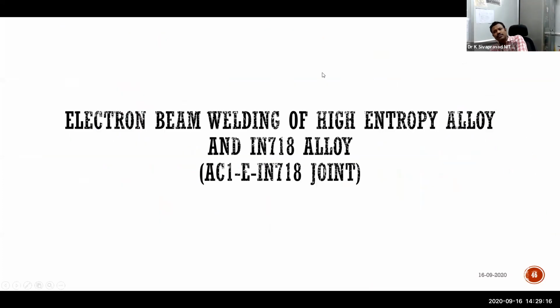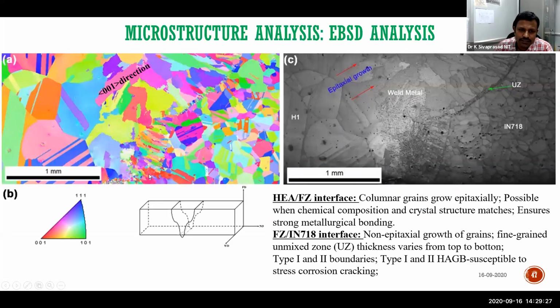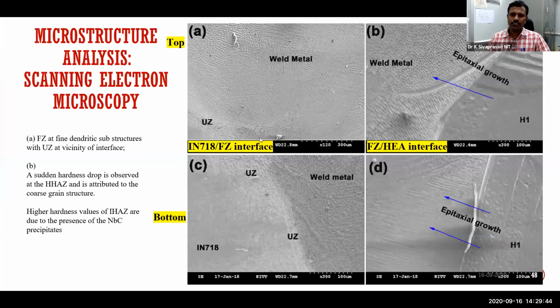Then electron beam welding of high entropy alloy with Inconel 718. The earlier combination was also high entropy alloy with Inconel 718, but that was GTA welding, and this is electron beam welding. And with orientation imaging microscopy, here also on the HEA side it is showing 001 planar direction columnar growth, that is epitaxial growth. Very clearly it is observed and demonstrated. But the fusion zone was very fine compared to GTA welding. See, the cellular structure size used to be very fine. And finer structures, we know, are always expected to give better properties.